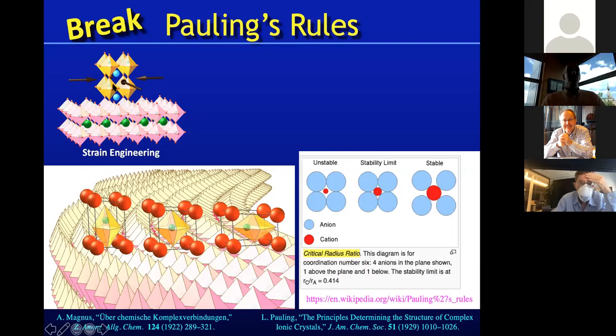Now, if we think about what that's going to do to the atoms that are inside of these octahedral cages, let's consider this case here. Let's say that this case that I've shown here in the center, the one that's unstrained, is at Pauling's stability limit. So in that case, the green cation, and if I think about the anions that are around it, this octahedron on each of its vertices has an oxygen, which I'm not showing because there are so many oxygens in this picture. I'm just showing the vertex, and at every vertex, there's going to be an oxygen. So the coordination polyhedron around this, and let's say there's ruthenium in the middle, for example, is an octahedron.